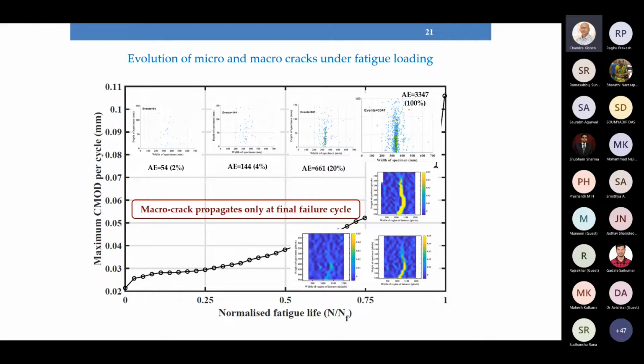In the next 25%, that is up to 50% of the fatigue life, only 4% of micro cracks have formed. The reason for this is that the amplitude of loading is smaller. We have not gone up to the peak. It's about 80% of the peak in this figure. Although 50% of the life has passed, still the number of micro cracks which are formed is very much lower.